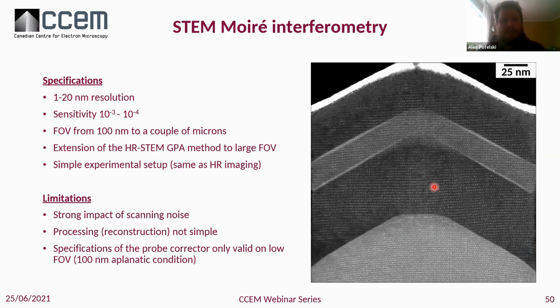What you gain here is the huge field of view, from 100 nanometers to a couple of microns. The sensitivity is 10 to the minus 3, 10 to the minus 4. So I would say it's slightly worse than the nanobeam diffraction. And you have a resolution that is going from 1 to 20 nanometers, can be actually large. It's just an extension of the GPA method to large field of view. And it's a simple experimental setup.